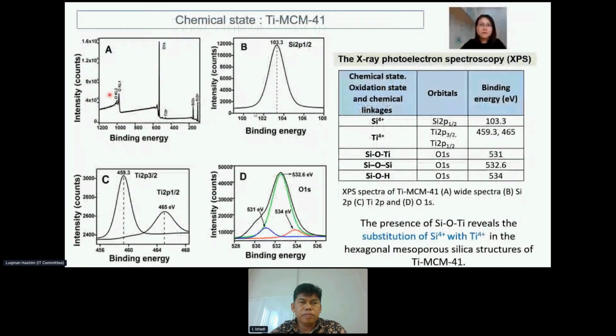The oxidation and chemical state of the surface elements, and also the type of the chemical linkage that is available for this modified titanium MCM41 support, was determined by using the XPS analysis. So based on the analysis, this indicates the presence of the linkage between the silica oxygens and titaniums, which reveals that there are substitutions of the silicate ion with the titanium ion, especially in the hexagonal mesoporous silica structures.